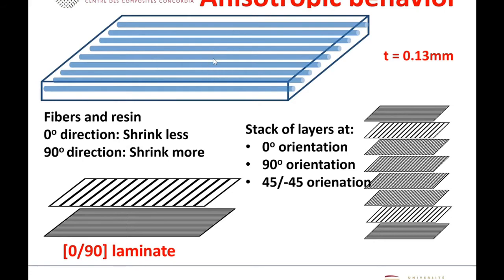But one particular aspect that we are looking for in the case of 4D printing here is the shrinkage. That means that when you heat or when you cool this material down, along the fiber direction it doesn't expand or contract as much, because it's controlled by a lot of these stiff fibers. But transverse to the fiber direction, it expands and contracts a lot. The expansion and contraction may be 100 times bigger along the transverse direction than along the fiber direction. So that is the case of anisotropic behavior of the layer.